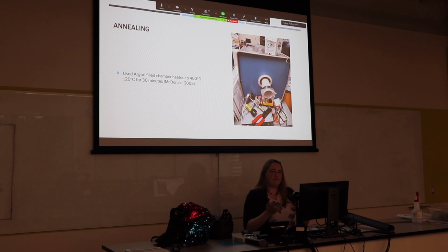Annealing is basically just baking your sample, but we don't want any oxygen or anything else that's in the air to react, so we filled our tube chamber with argon and then heated it to 400 degrees Celsius for about 30 minutes, which we got from a prior SFA master's thesis in 2005.